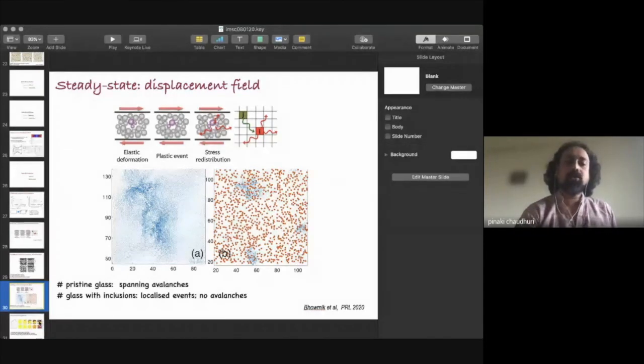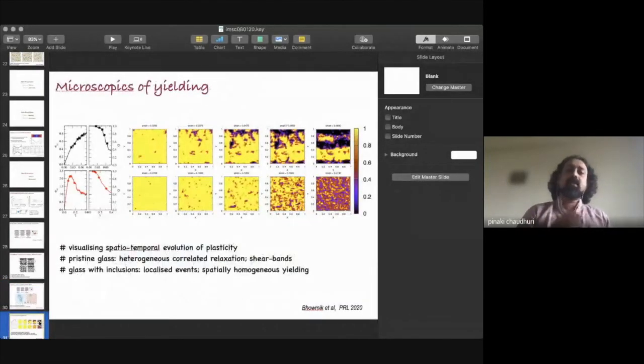The consequence of this is that it has a larger strain threshold. It also has a larger yield threshold, and it also has a very different kind of spatial morphology in which eventual failure happens inside the system. For example, if I take a pristine glass, you have a very spatially heterogeneous response, what are known as shear bands. But if I impose spatial constraints in the form of pin sites, this heterogeneous response is completely destroyed, and you have a much more homogeneous response, where the system evolves in a spatially homogeneous manner before it starts flowing, and so on.